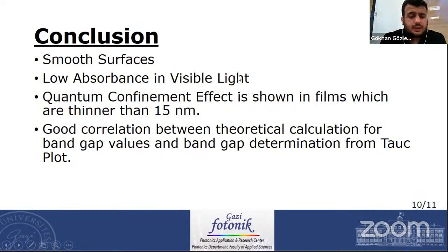I want to conclude my presentation. All samples which have thicknesses from 5 nanometers to 35 nanometers have average roughness lower than 0.5 nanometers, and they are perfectly smooth. Films are also transparent in the visible region, and transmittance reduces with increasing thickness. Also, the absorption edge shifted to the blue region within thinner films, and it's correlated with the quantum confinement effect. Quantum confinement effect is shown in films which are thinner than 15 nanometers. Beyond this thickness, carriers move freely, and the quantum confinement effect isn't shown. There is a good correlation between theoretical calculation for band gap values and band gap determination from Tauc plots.